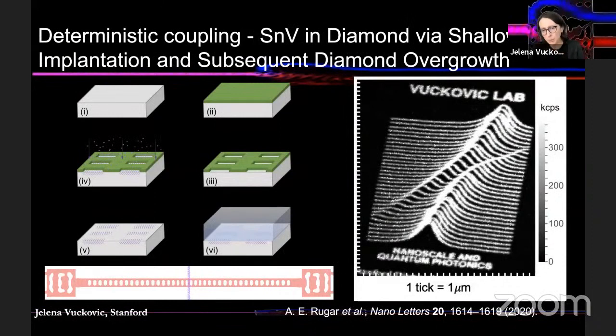So at the moment, for addressing spatial inhomogeneities, we use a method of growth we developed together with Zi-Yuan Shen and Nick Melosh at Stanford, which we call shallow ion implantation and subsequent overgrowth. The idea here is to incorporate these impurities at the desired position in the diamond lattice with minimal damage to the lattice. Because if you do it the way people normally do it, with very energetic ions, then you damage the lattice, and that leads to a large spectral inhomogeneity. So we don't want to do that, which is why we're doing it at very low energies. So we go from 300 kiloelectron volts to 1 kiloelectron volt. And when you do it at 1 kiloelectron volt, then you can easily produce a mask on the chip with electron beam lithography and just do implantation at desired positions, as we do here.